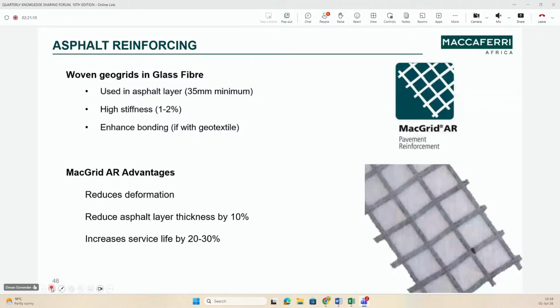The roads become so badly rutted that you can see key parts that have been formed in the road that we need to drive on. And when we start looking at the principle of rutting, and this is really what we're addressing here, it becomes a bearing capacity failure. So the entire pavement layers can't take that load anymore. You start getting differential settlement. There's some rutting that occurs. Wet also contributes to it. There's weak subgrades, and you counter this with thicker layers. And that's really what you do when you're starting to look at this. This is in the absence of putting in a synthetic material.